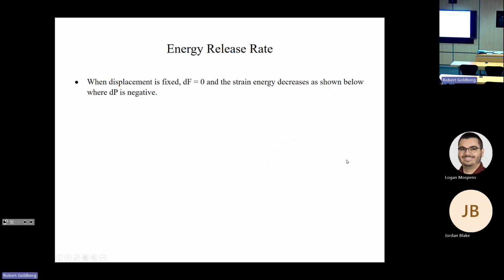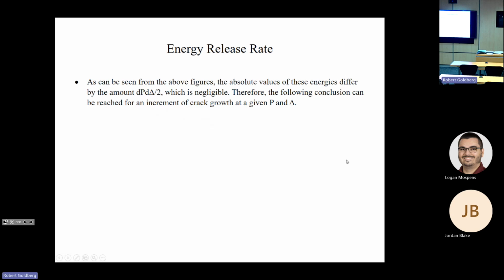And conversely, when the displacement is fixed, the change in the work due to external forces is 0, and we can also get that the change in our strain energy due to displacement is equal to the differential of the load times the displacement divided by 2. And this change in load term is negative. So the absolute values of these energies differ by an amount, dP times d delta divided by 2, which is negligible. So what we can say then is, for the cases of load control and displacement control, the change in strain energy due to load control is just the negative of the change in strain energy due to displacement control.